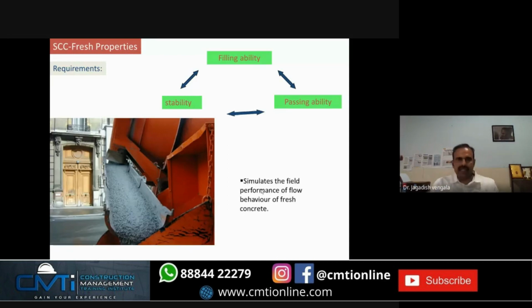So coming to another important part of my presentation, that is fresh properties, very, very important. In general, for normal concrete, we make the mix and then place it in a slump cone, Abrams cone, lift it, and check the vertical slump, or sometimes you do a VB meter test, or sometimes other tests, very few tests, but the most common is the slump cone.